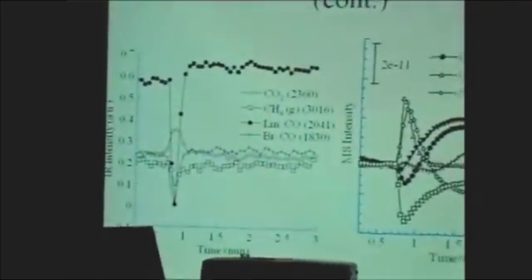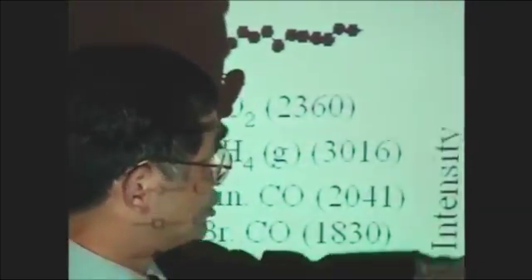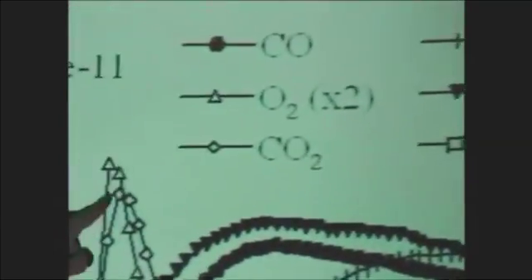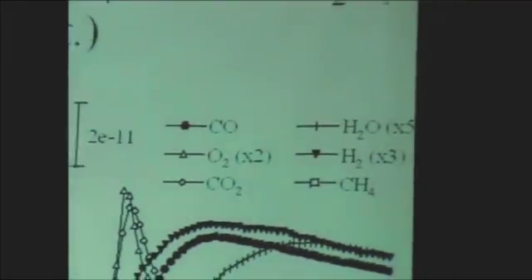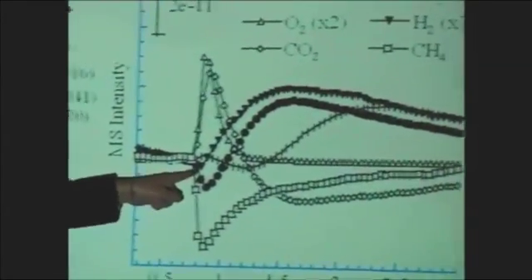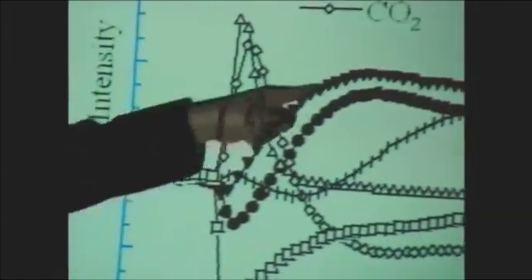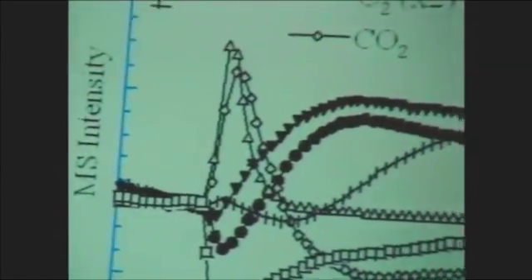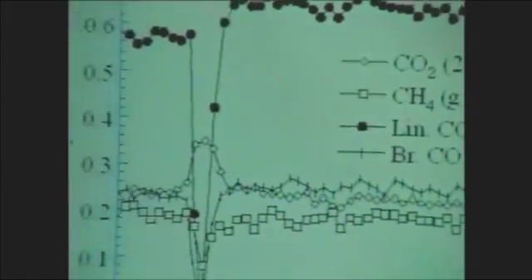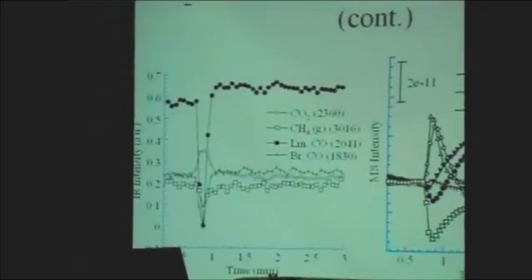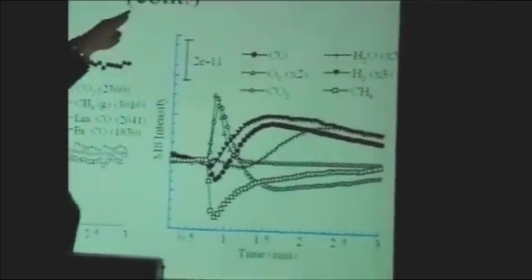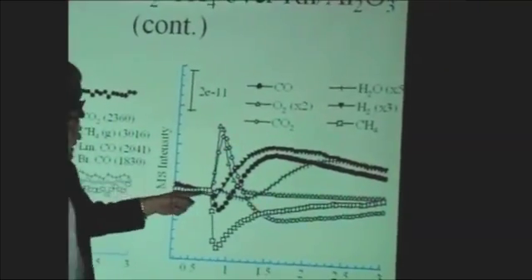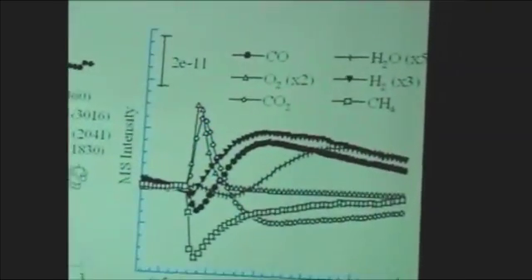And if we follow the mass spectrometer here, we'll see that when oxygen comes in, this triangle is oxygen coming in, it immediately induces CO2 formation. After CO2 is formed, then we see the formation of hydrogen and the formation of the CO here. This is CO, this is hydrogen. Again, we can see in this reforming reaction, in the reforming of methane by CO2, hydrogen formation is a much easier step. The methane can easily be activated and generate hydrogen here.